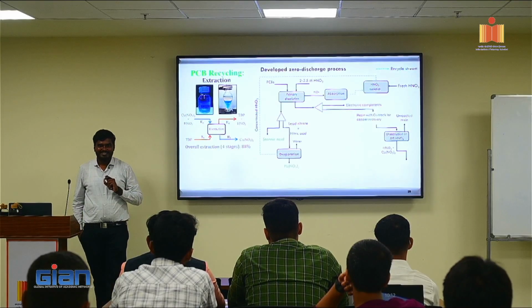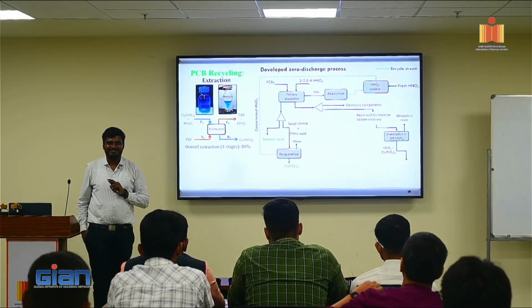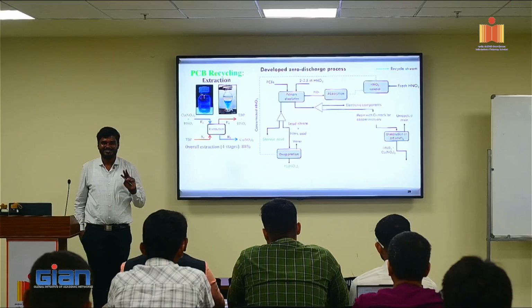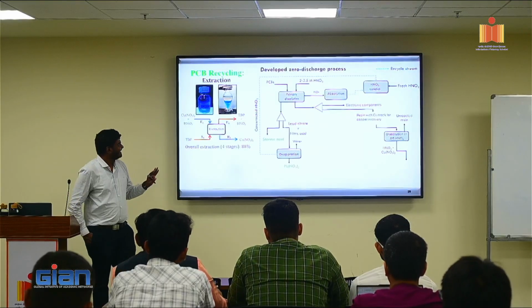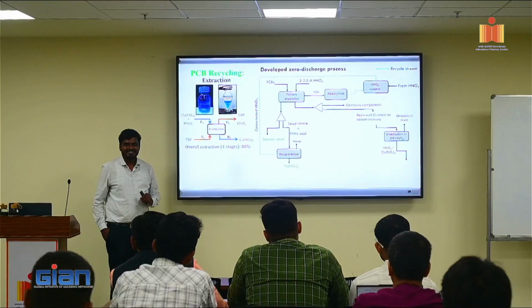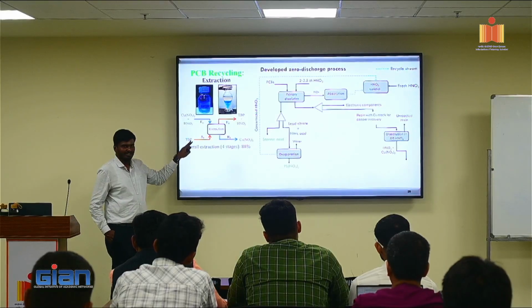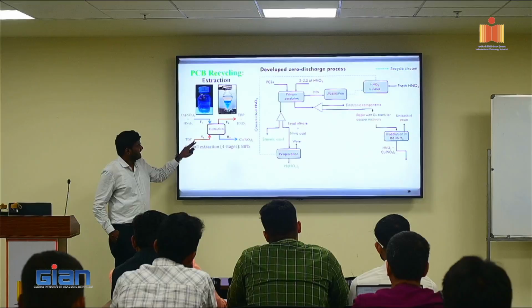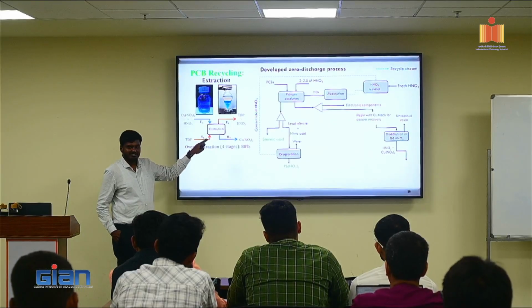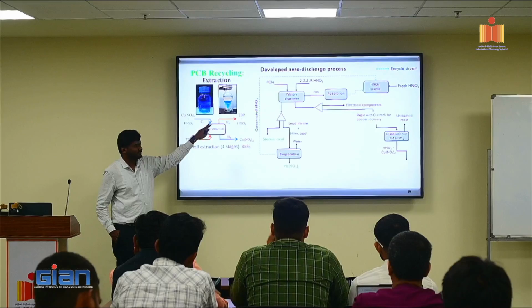I want to separate copper nitrate and nitric acid, and I don't want to go for electrodeposition. Reason why? No more additional chemicals. So we thought, can we do liquid-liquid extraction? So basically, if you use tributyl phosphate, what actually happens is, tributyl phosphate is an organic solvent. It tries to extract nitric acid from this solution.